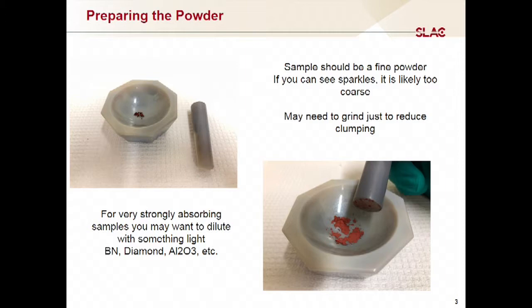If you put in something that has a very well-known thermal expansion, you can actually use this to calibrate the temperature of your sample and not just where the thermocouple that's close to your sample is reading. So you can actually get much more accurate temperatures this way using an internal standard.